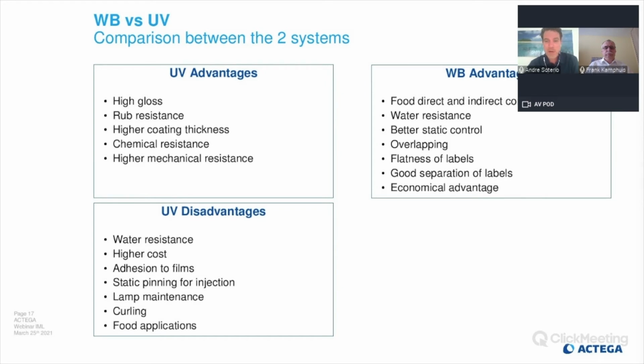It has a better static control during the printing and die cutting. When you charge that with static, and we're going to see that later, the label will stick on the mold. That's one of the main reasons why people use water-based coatings, because it's a very reliable system. This is not a very popular or defining property of the coating, but a lot of people want a very nice overlapping of the label. If you think about margarine labels, margarine tubs, it always has some overlapping on the sides, and people want to see a very nice overlapping, and water-based coatings can provide these properties.